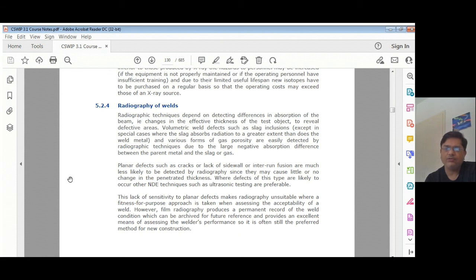Planar defects such as cracks or lack of sidewall or inter-run fusion are much less likely to be detected by radiography, since they may cause little or no change in the penetrated thickness. So cracks and lack of sidewall fusion are very difficult to find in radiography, but if it has some kind of thickness, it will be easily seen. But usually cracks are very tight, and when the beam passes through, there will not be much change in the beam disposition on the film. So cracks are very difficult to find in a radiograph. Ideally, UT is the best method to detect cracks.